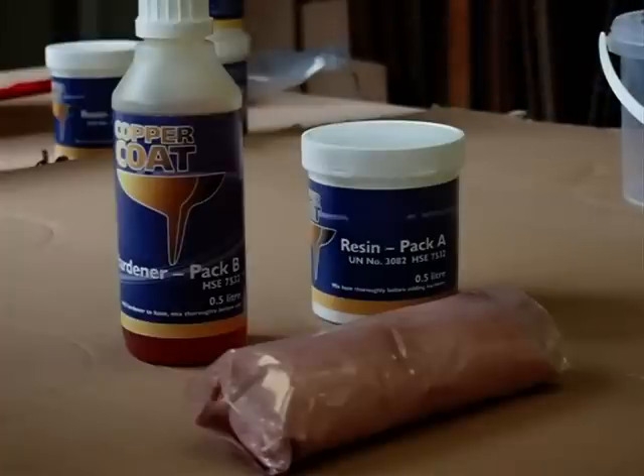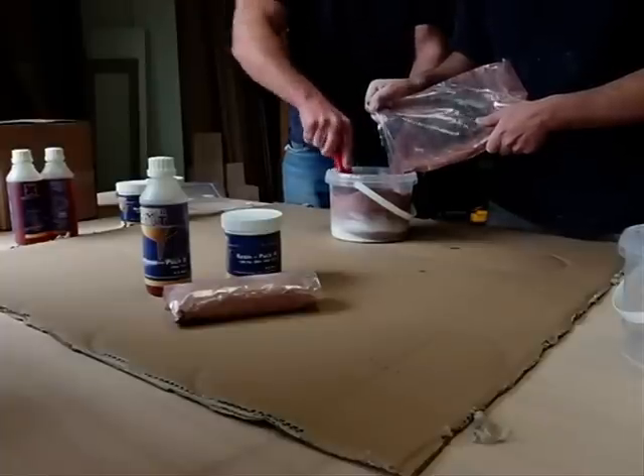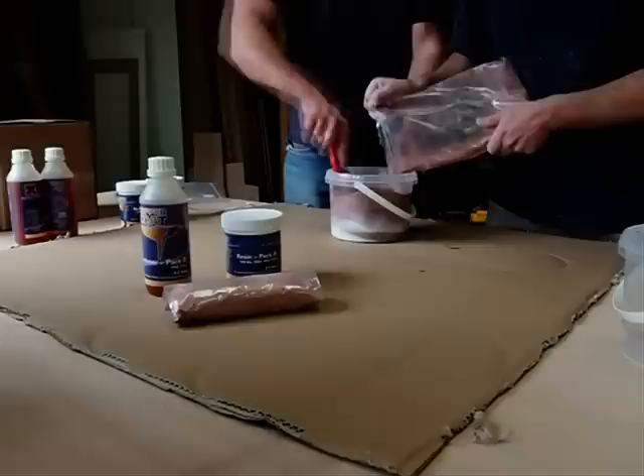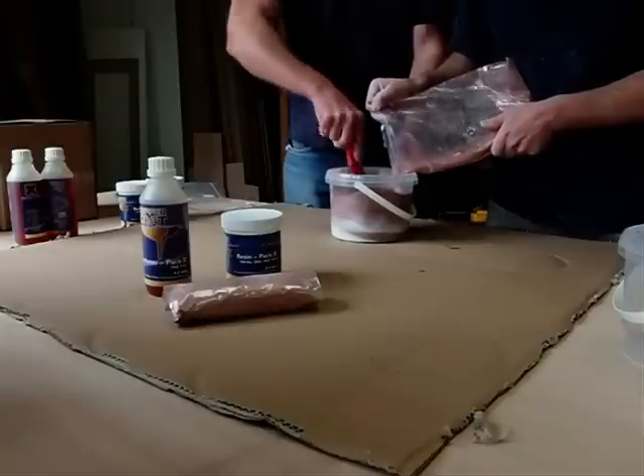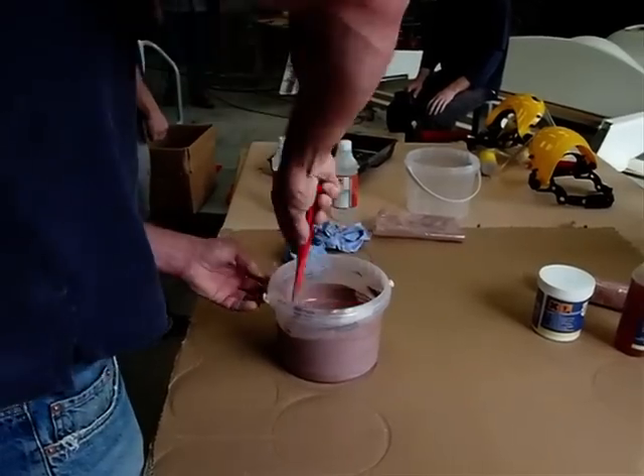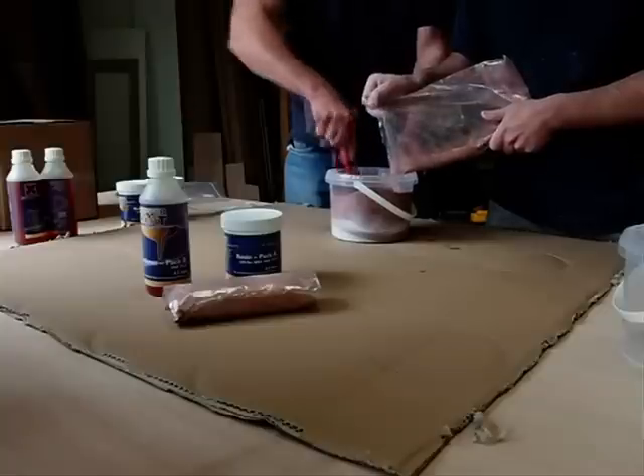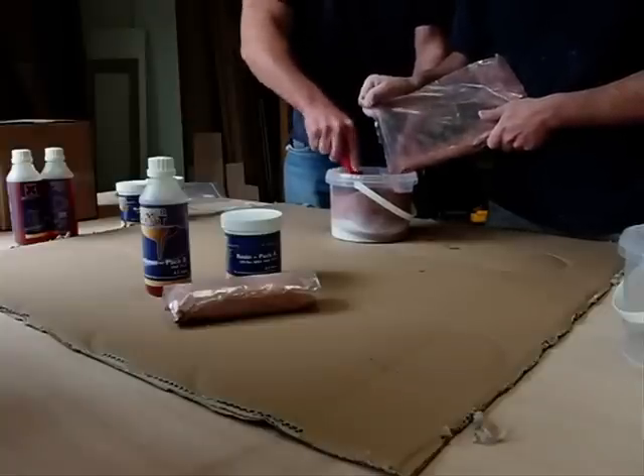Coppercoat is the combination of a specially developed solvent-free epoxy resin and high-purity 99% copper. Each litre of resin is impregnated with 2 kilos of ultra-fine spherical copper powder, the maximum quantity allowed by current pesticide laws, making Coppercoat the strongest copper-based anti-foul available.